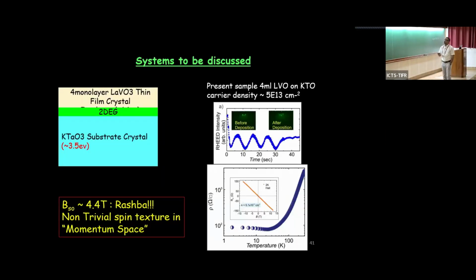So we have grown lanthanum vanadate on top of potassium tantalate. And we are showing the data of 4 monolayers of lanthanum vanadate grown on potassium tantalate. So how do you judge the number of monolayers grown? We are judging it from the reflection high energy electron diffraction system. You can see exactly 4 oscillations come, and then we stop the growth. So it means you have 4 monolayers of lanthanum vanadate on potassium tantalate.